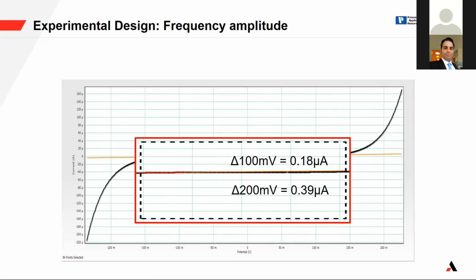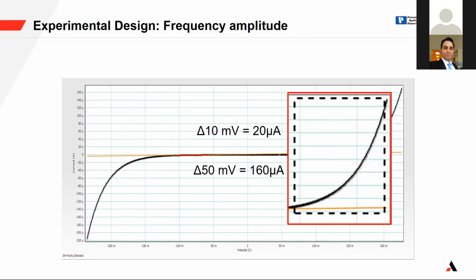Okay, what happens if I analyze the second part? 10 millivolts give me a current of 20 microampere. 50 millivolts, 160 microampere. I'm in non-linear condition. So what it means is that I need to be careful, and maybe instead of using 10 millivolts, probably it's better to use 5 millivolts or 2 millivolts. So not using a big amplitude, because I will generate a lot of current. Okay, so remember, the amplitude belongs to this fact.